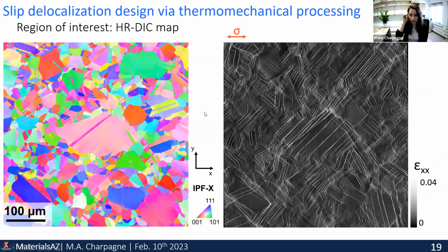When we look at the slip band pattern here, this is the full map. So we mapped a 500 by 600 microns region. You can see the signature of many slip bands. So I just want to remind you here, the more slip bands, the better. We're just barely beyond the yield point here in this material, and we have a lot of slip bands that formed. And we want to look into whether we still have those intense slip bands near twin boundaries. So we have here, for example, one twin boundary and here another one. So in the following, I'm just going to detail what happens near these twin boundaries and how the morphology of the slip bands has changed as a result of this modified process.